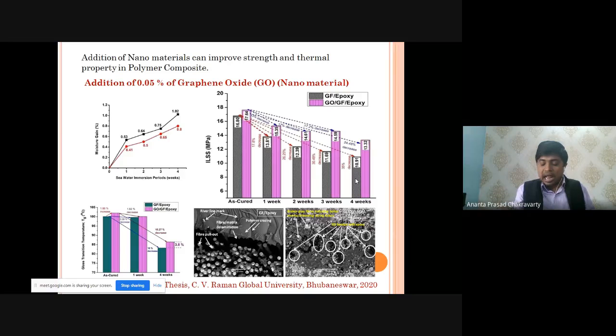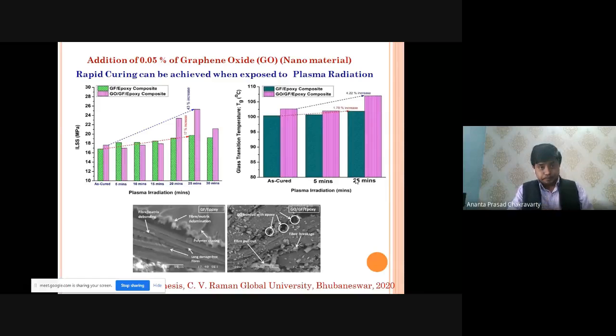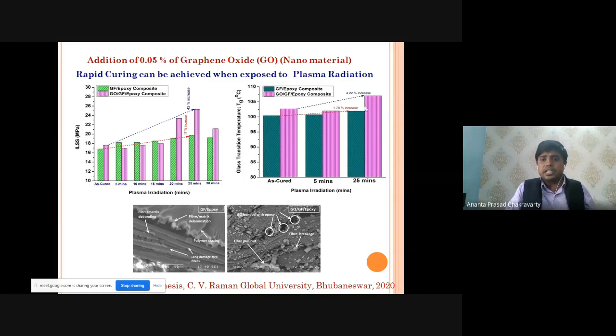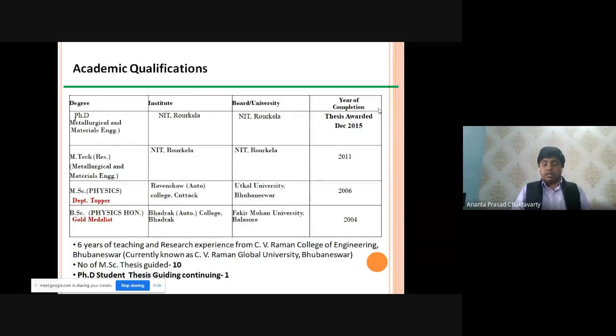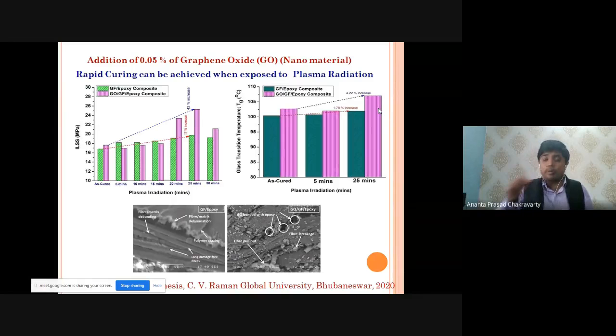So very crucial. Hence this was published in a very reputed journal. With the addition of 0.05% graphene oxide, I exposed the glass fiber reinforced polymer composites to plasma radiation, and in the presence of graphene oxide its properties improved by 4.22%. That means I can control the properties of the composites by incorporating nanomaterials, or by suitably choosing their curing techniques. All these are my research areas. I have completed many research things, but time is a factor for us.